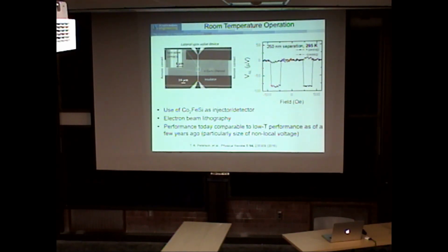The comment here was that this is what was happening 5 years ago. This is what got our low temperature. So it really does work. I'll make an interesting comment here. Cobalt-2 iron silicon works. It gives a lower spin signal, but lower noise than if you use cobalt-2 manganese silicon. We believe the manganese is doing a little bit of diffusion into gallium arsenide, and I've shown some SIMS results, and it's actually giving us more noise, although a larger signal.